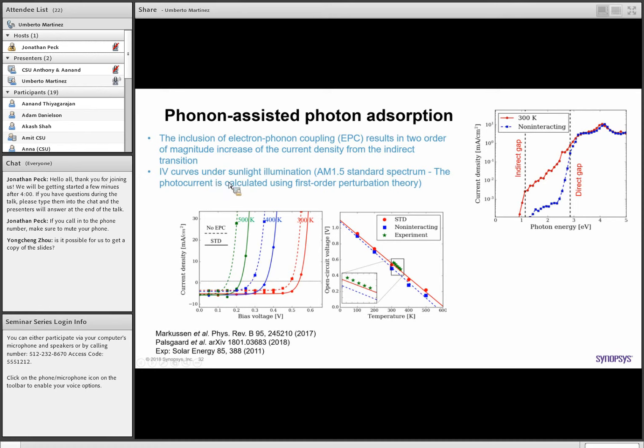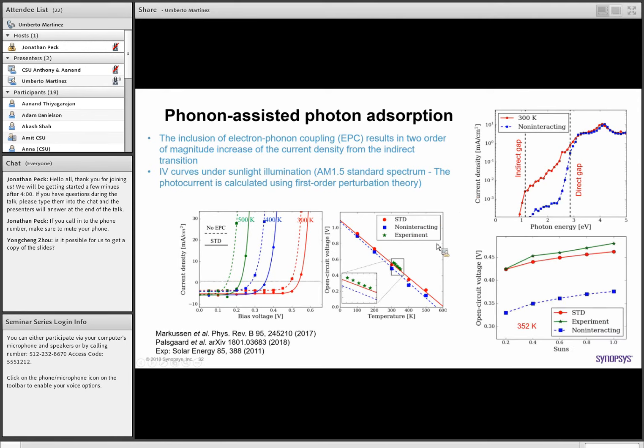We can also calculate the photocurrent, using first order perturbation theory, and I refer you to these references for the full details of the theory. We can study here, for example, the IV curves at different temperatures, with or without electron-phonon coupling, and by the intercept at zero current we extrapolate the open circuit voltage, and then compare with experimental data. We show that you do need to include finite temperature effects in order to catch the experimental results.